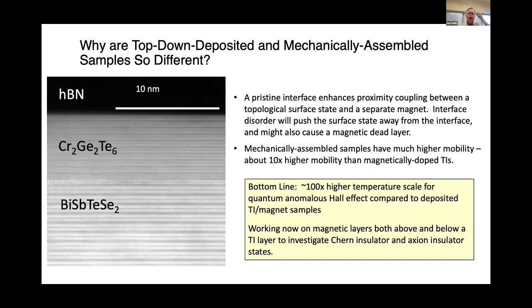Okay, so why are these mechanically assembled samples so different from the top-down deposited samples? Well, with the mechanical assembly, you really do have extremely pristine interfaces. And here's a nice TEM image from David Muller's group at Cornell. And I think what happens is with deposited structures, if you have any intermixing at the interface, that scattering will push the topological surface state further into the bulk of the topological insulator and decrease the exchange coupling to the magnet. So I think having pristine interfaces really does make a large difference in terms of the temperature scale at which you can begin to see the quantized anomalous Hall effect.